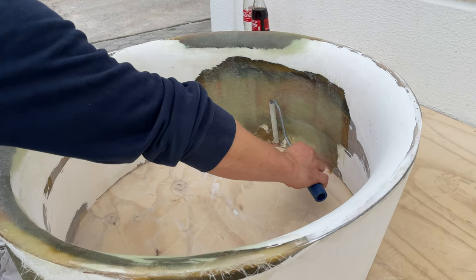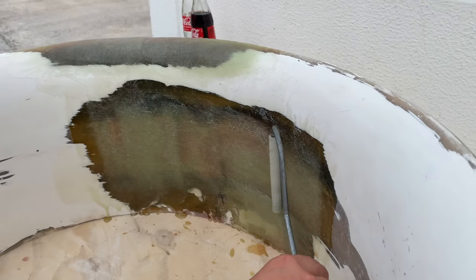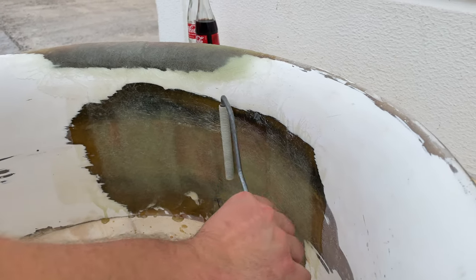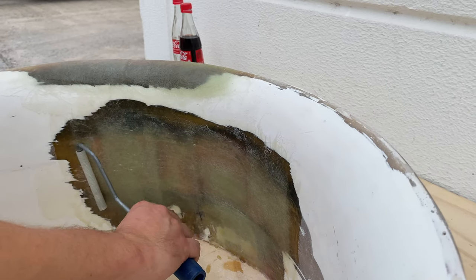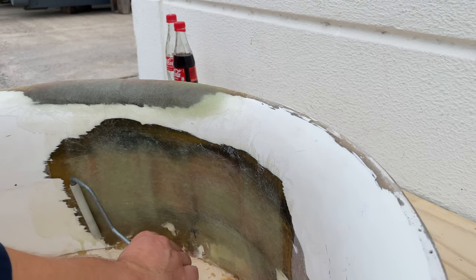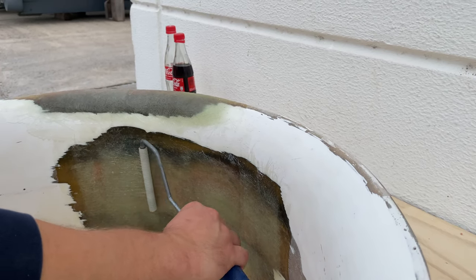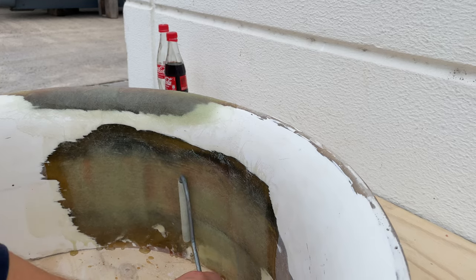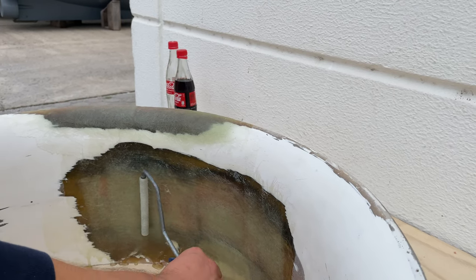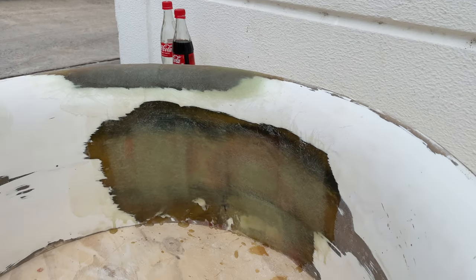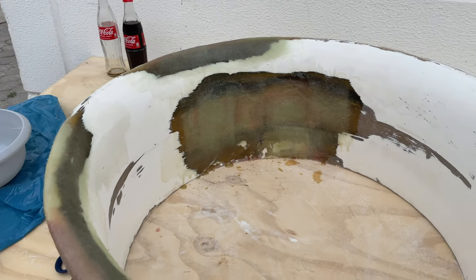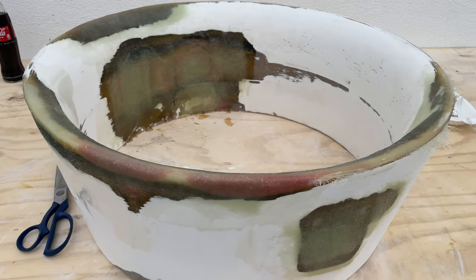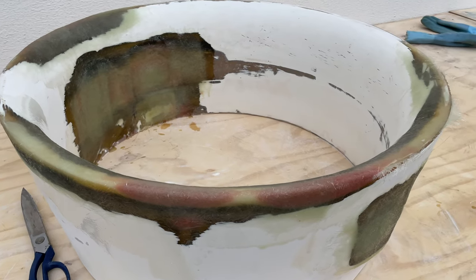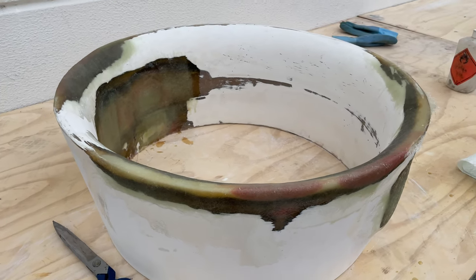Here it's very important to find the right pressure point. So if you put on too little pressure, air bubbles will stay in the material and you'll have spots that are weaker than others. If you put on too much pressure, you're gonna push out all the resin and therefore you'll be left with fiberglass that isn't properly laminated. So it takes a bit of practice.